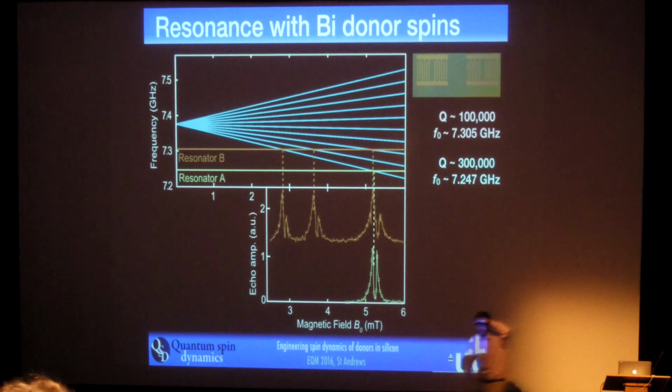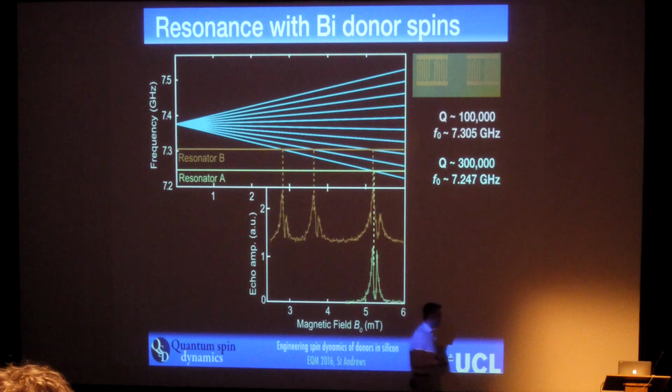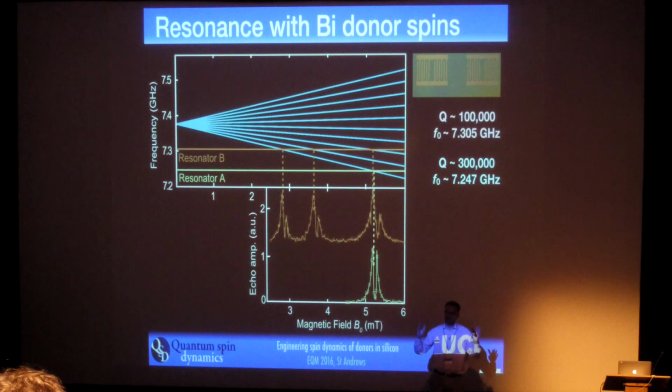So I was wondering if you can reach a density or see effects where the bismuth atoms are so close together that you get exchange interactions? Yes. That's been seen for various donors. The signature is, first of all, the effective hyperfine coupling starts to fall, because the electron spin is sampling different donor nuclear spins and views some kind of average.